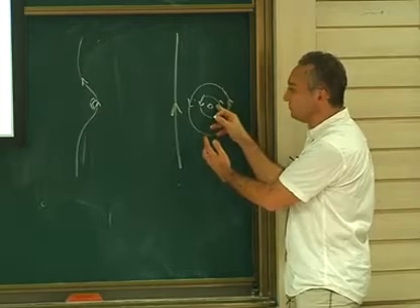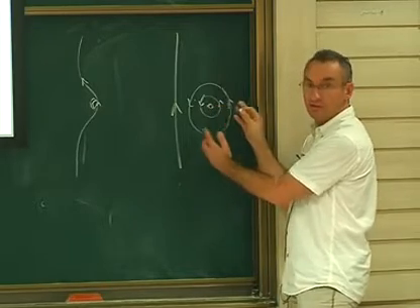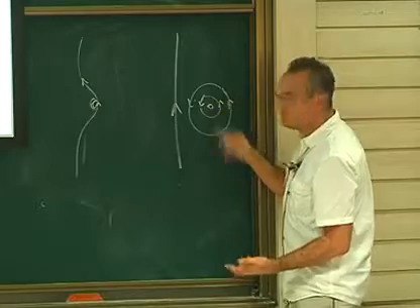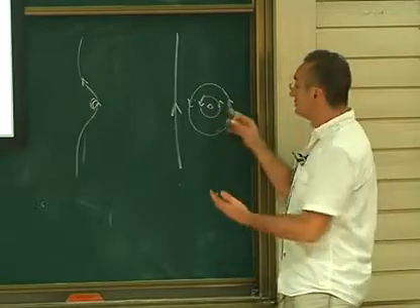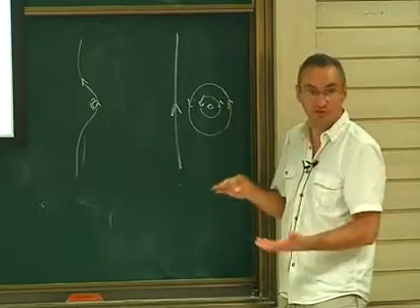So the stress on the first dislocation is even higher than the applied one. It's the applied stress times the number of loops deposited. So it's very easy to shear particles if you have a couple of dislocations surrounding them, because of this mechanism. It's just a geometrical effect, but usually we neglect it, just because the applied stress wants the dislocation to shrink.